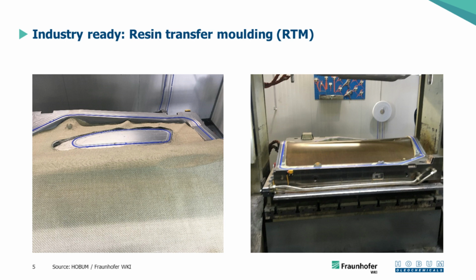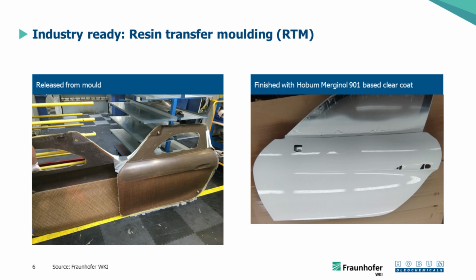The mold has been opened here. The mold is, of course, heated to roughly 130 degrees, and then you release from the mold, and you have one part of this door, the outer part. And on the right side, you can see also the finished product, how it's been mounted to the race car. The clear coat actually is also made of a Merginol 901, which is also based on natural products.